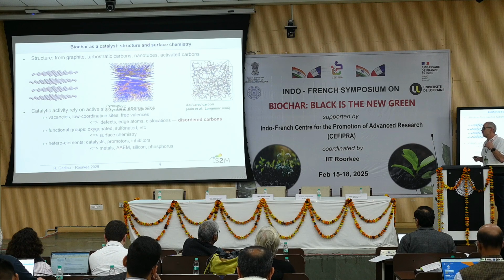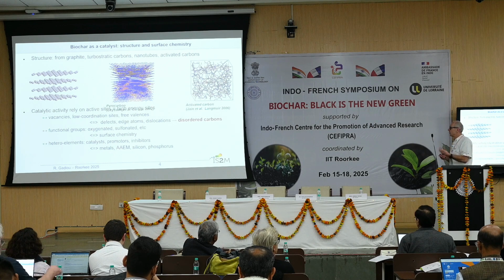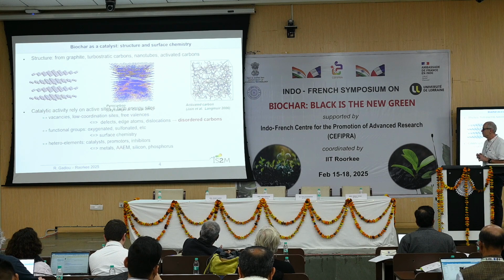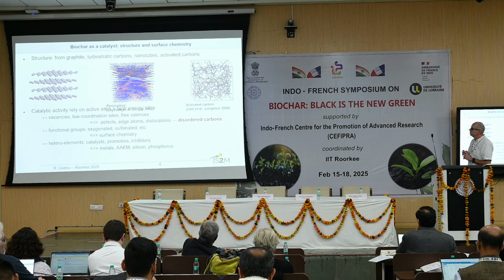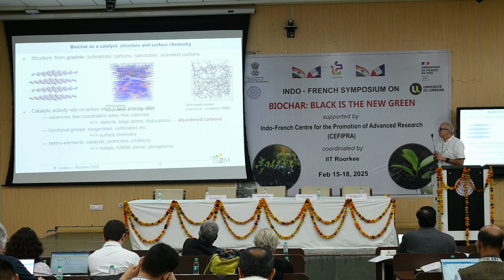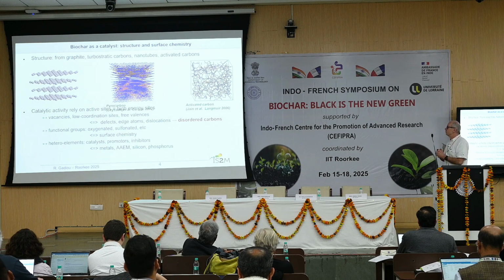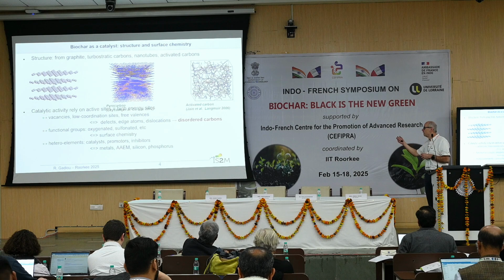If we come to what we expect to be an activated carbon, it's much more complex. Here, for example, you have a model which was done in USA some years ago, obtained by Monte Carlo simulation. And we see that we have an isotropic material which is nearly homogeneous without any stacking. This model also failed, since it doesn't take into account the actual structure of the carbon material, which should be between these two, between pyrocarbon and activated carbon.